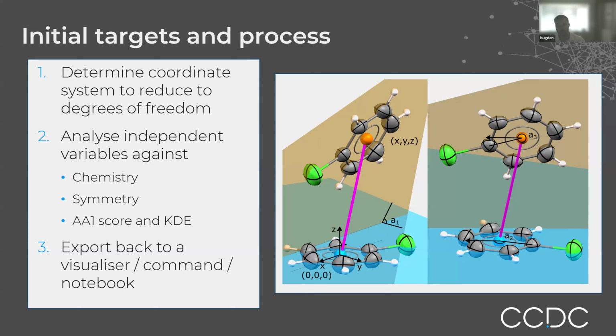And so there's a correlation between those two values, and you can see then that aromatic interactions are important. We can see from AA1 that they're low energy, and we can see from the KDE that they turn up in nature an awful lot. The tool will then export the information back to a visualizer or a command line or notebook, and users have found those three ways to interact quite useful.